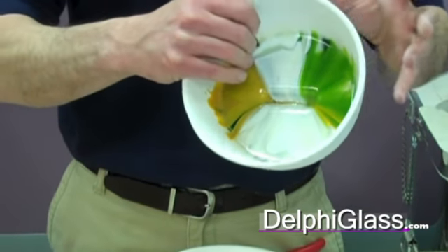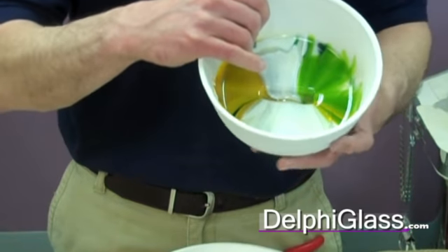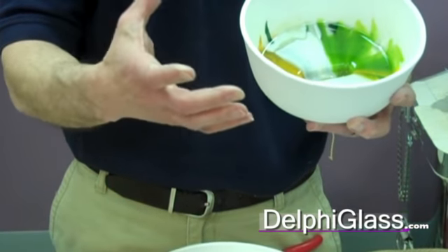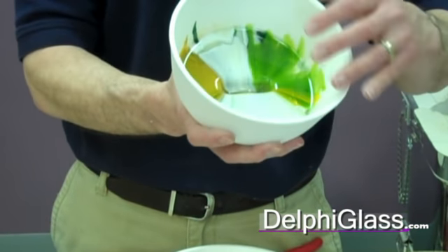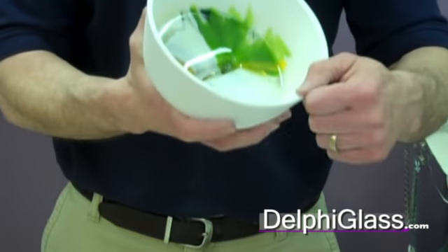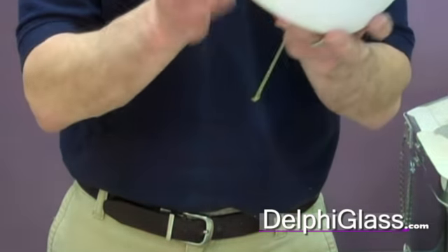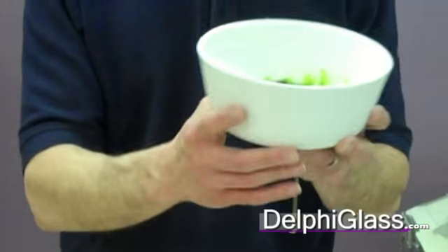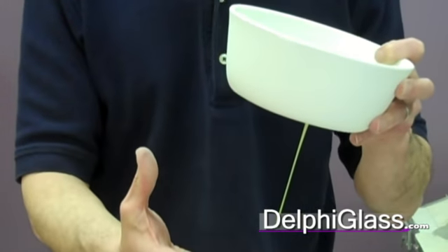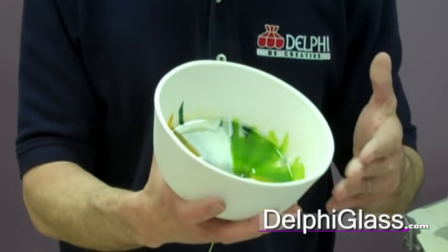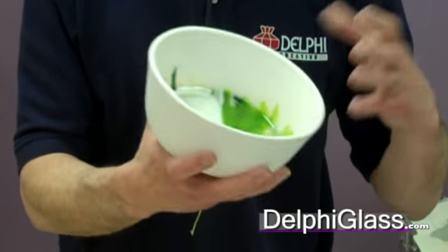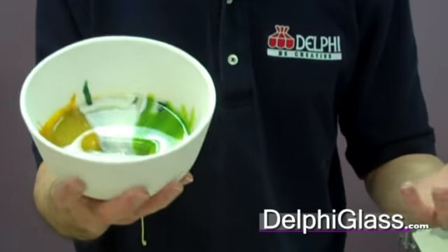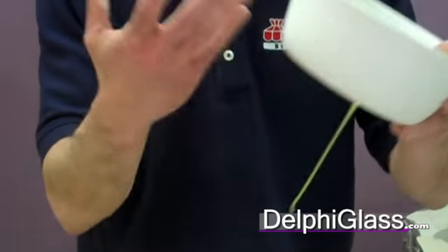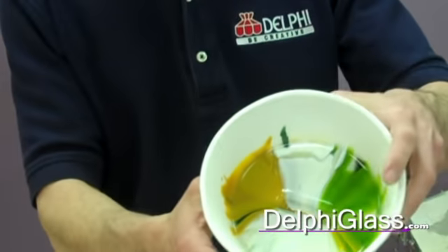Now, if you leave too much glass in the pots, what happens is as they cool, because of the difference in expansion and contraction between the glass and the ceramic form, the bottoms will crack and break and fall off. So you want to try to melt out as much of the glass as you can out of the pot, and the key to that is just holding it. When you're up at 1600 degrees, you want to hold it for about an hour to get the glass to come out. That's what this one was. I held this for an hour, and you can see there's hardly any left.